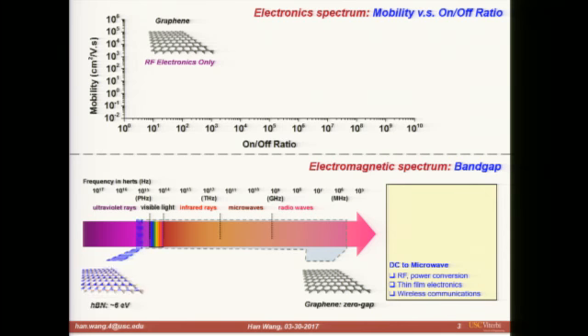On the other extreme, we also have hexagonal boron nitride, which is a 2D material with a band gap of around 6 electron volts, making it an insulator, so you don't see it anywhere on this electronic spectrum, but its band gap corresponds to a narrow region in the UV spectrum range.